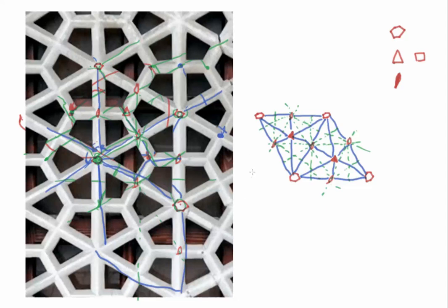In reality, once you find a number of symmetry operations, you can usually refer back to the crystallographic symmetry tables for plane groups. Because, for example, once I've found all these rotation axes and the mirror planes, there's only one plane group that has those, and that plane group also shows me where all the other glide planes are. So if I look at the tables, this is the plane group P6mm, and so this notation designates that it's a primitive unit cell.